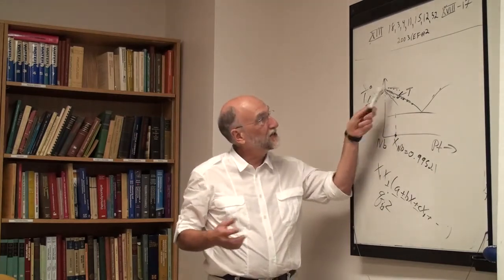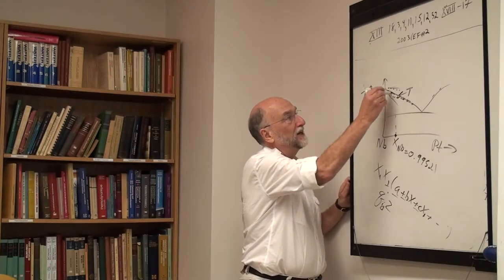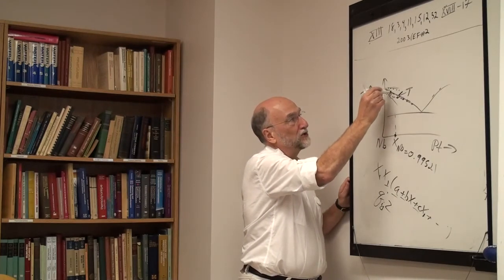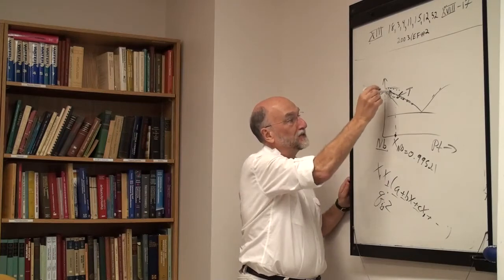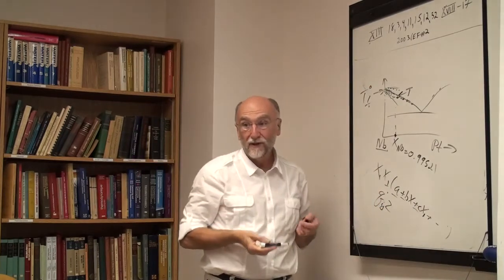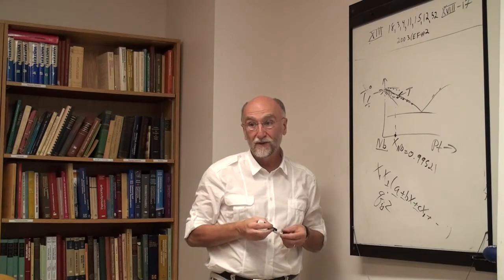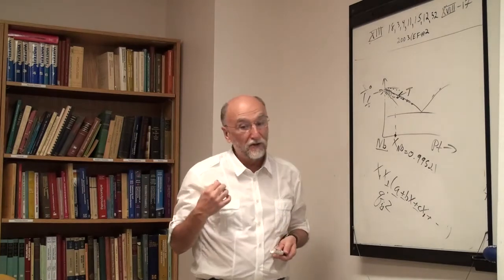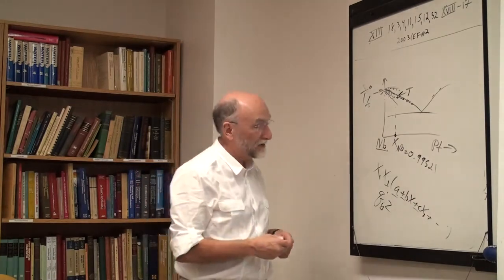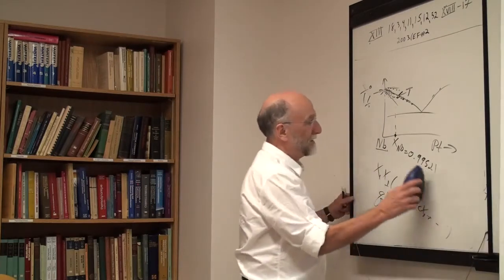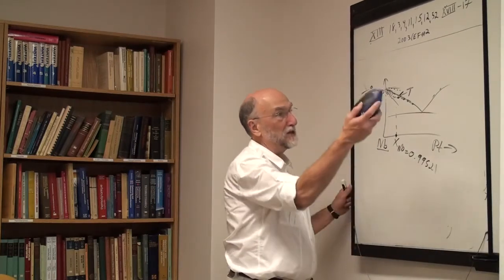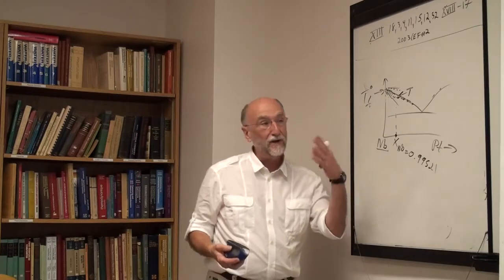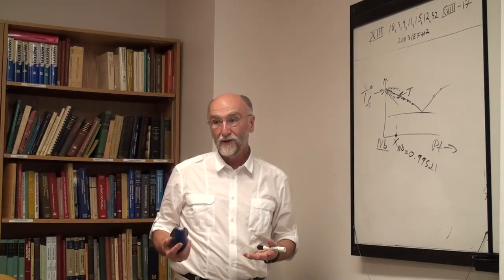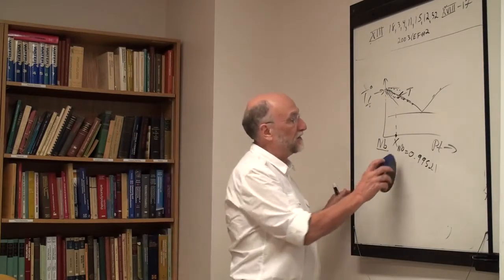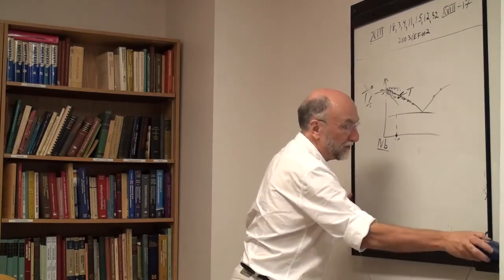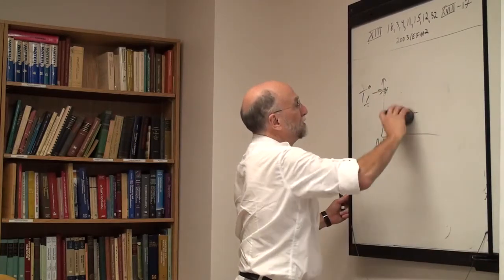Yeah. But G-excess in the liquid will, if you take the calculated liquid as here, the closer and closer you get to the pure niobium, the less and less effect any G-excess term has on it, only the ideal mixing term. Now we'll talk later, there is one thing where it does make a difference, but I don't want to get too far ahead of myself. And that is, it depends only on the ideal mixing term, the ideal mixing term being the configurational entropy term.